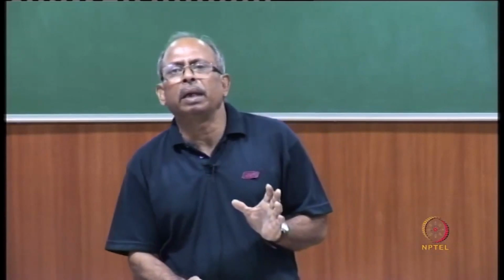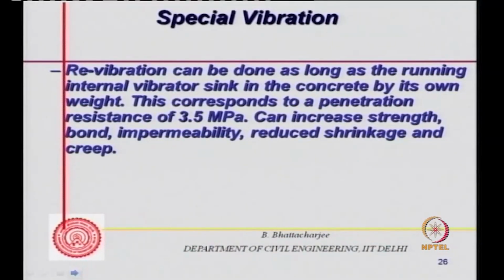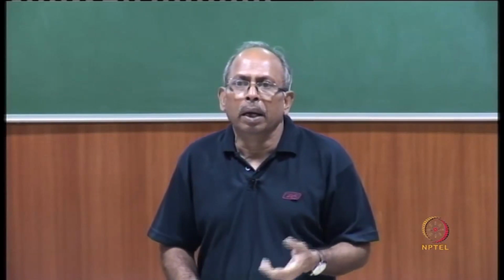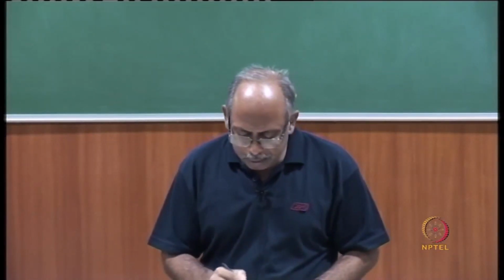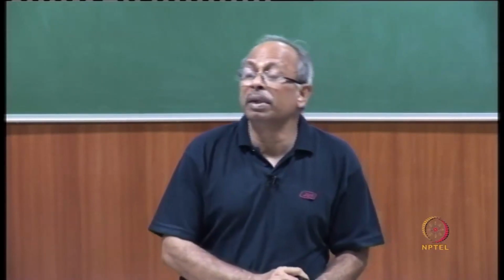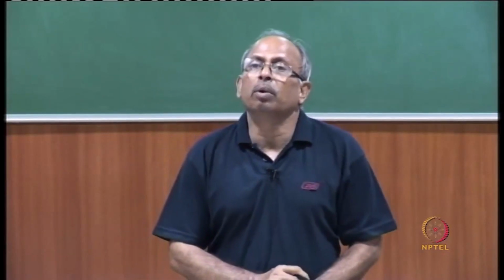Special vibrations are revibration and vacuum vibration. Revibration can be done as long as a running internal vibrator sinks into the concrete, at a penetration resistance of around 3.5 MPa. Now penetration resistance is a measure of setting, and it should be 3.5 MPa. If it is more than that, then you cannot use it. It can increase strength, bond, impermeability, and reduce shrinkage and creep. So revibration is not always desirable, but you can do it as long as the concrete is not set.